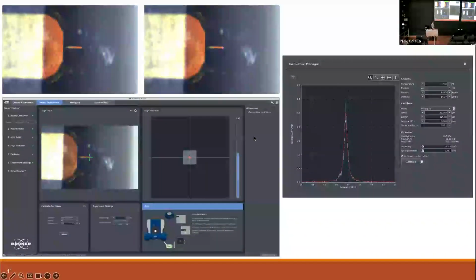This is what the software looks like and kind of the interface for that. So we have our cantilever here. We're going to place the laser, which is this little pink spot, onto the end of the cantilever so we can monitor its location. And then we're going to align so the reflected light bouncing off that cantilever is exactly in the middle of our detector and that we're getting good signal with the blue bar on the right. We're going to oscillate that cantilever in air and look at its frequency response. And from that, we can back out the calculations for the sensitivity, which is how much the probe is moving up and down, and the spring constant, which is how stiff the cantilever is.